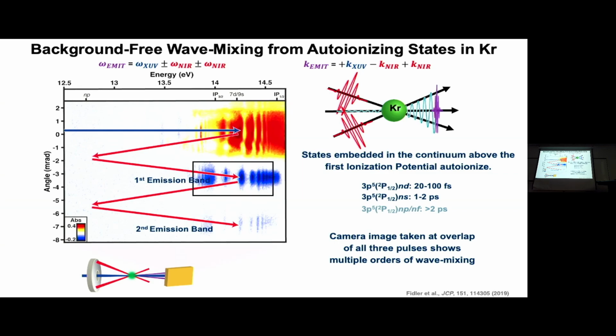And also the photons? Photons, all photons. And so, for example, if we put in an XUV and have the two beams coming at different angles, we can go, say, from this region down and then back up and get an emission. And it comes out at a new angle. What's exciting about this is that it's called background free, because you're not blinded by the main XUV beam. You're coming at a new angle where there was no emission before.